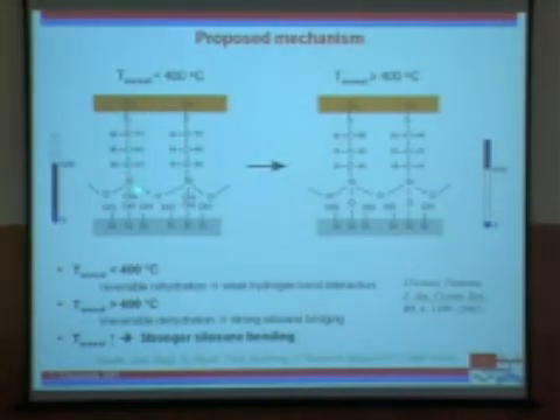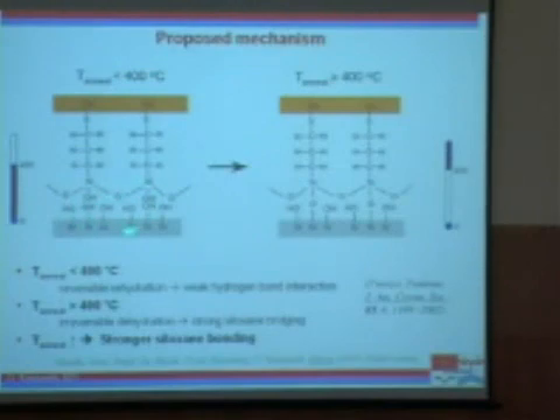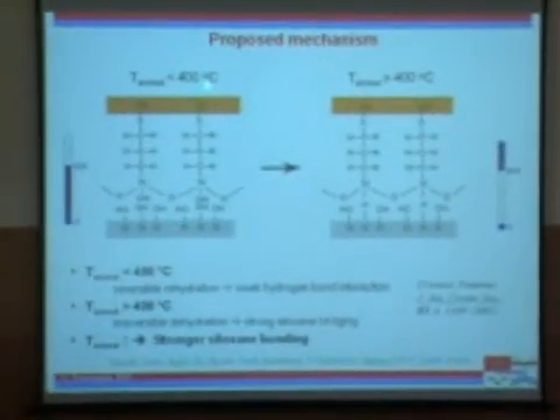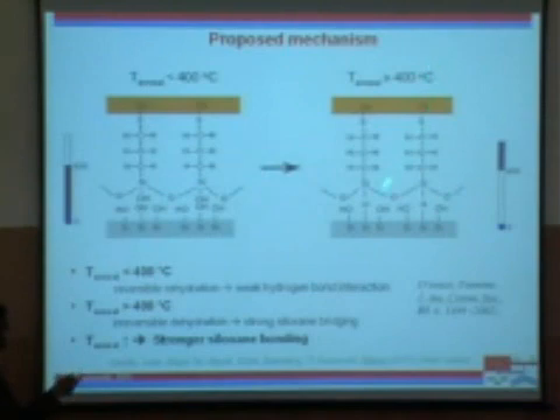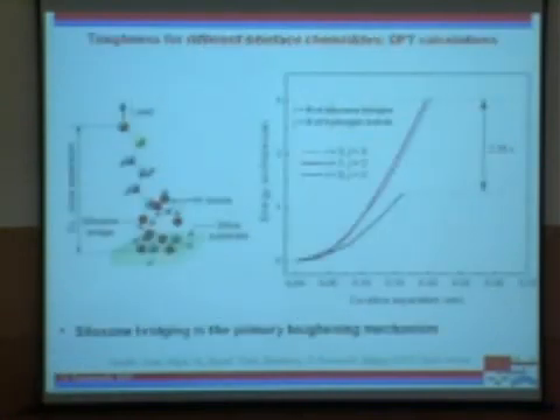At low temperatures, when you anneal it, this part of the bond actually stays stable, and this part, however, is unstable. The OH groups that you have on the silicon actually tend to form SiO-Si bonds, but they revert upon cooling. Okay, so the bonds formed here are reversible for less than 400 degrees centigrade. So this remains a weak link. Okay. And over here, though, at higher temperatures, the bonds that are formed stay put, and they are stable, and they do not revert to the SiOH bonds, and hence you have a case where both the interfaces are strengthened remarkably.